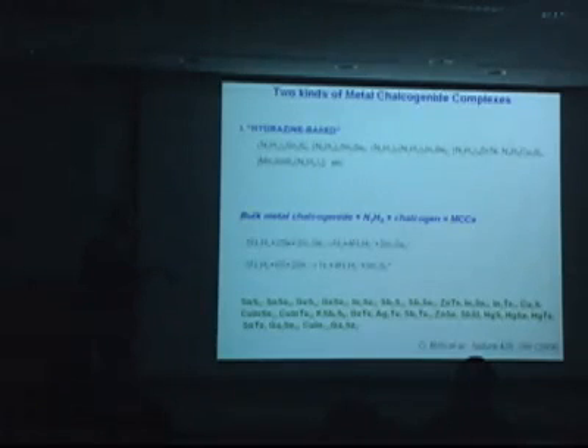But at the same time, I want to emphasize that for practical applications, hydrazine is not good, and it raises many scalability problems. So there is nothing special about hydrazine. We can do the same chemistry using very simple, aqueous type preparations. And we can make, for example, arsenic chalcogenides, tin chalcogenides without any hydrazine, and it works equally well.